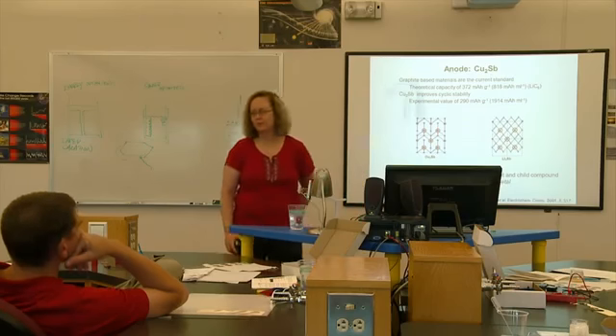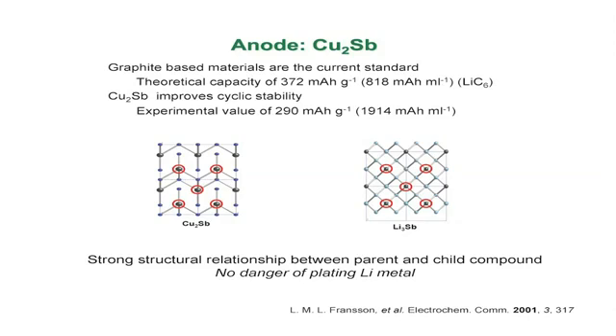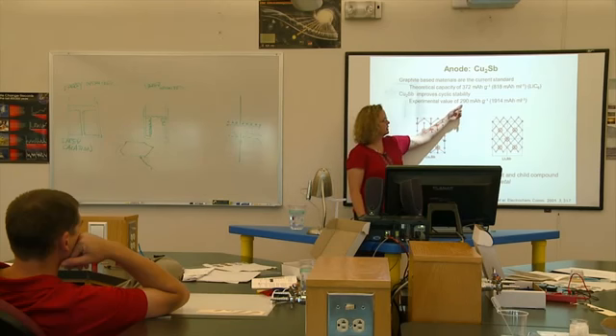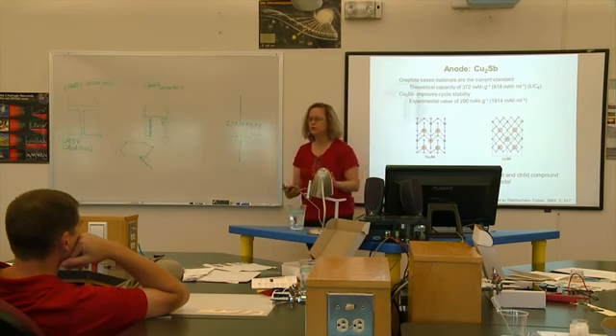So this is the anode we use, copper antimonide. Antimony is not probably something you would want to eat a lot of, but it's in the same family as arsenic, but it doesn't have the toxicity that arsenic has. This is the only part of the battery that you could probably argue is not truly non-toxic. But when it's in that compound, it's actually very safe. Now, graphite, if you think about mass, has a capacity of 372 milliamp hours per gram. Copper antimonide is lower than that, it's 290, and that's because antimony is such a heavy element.